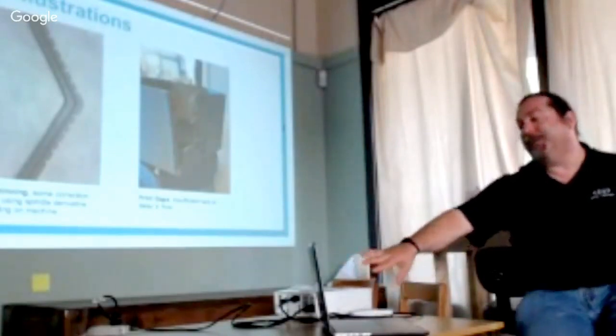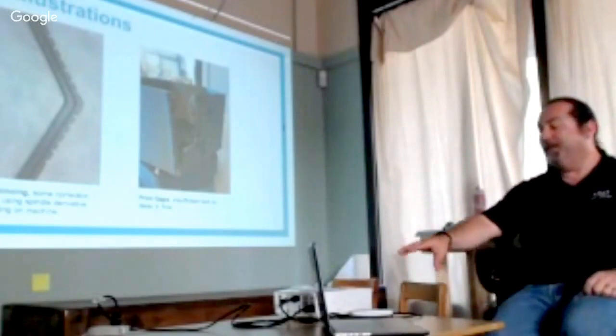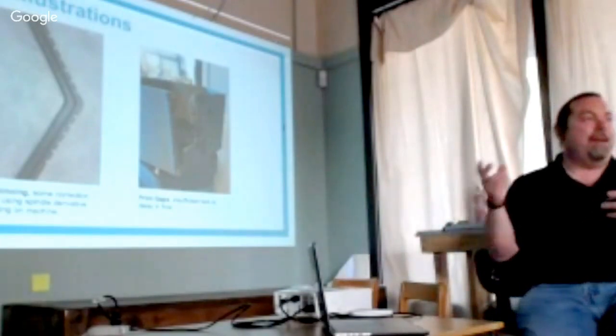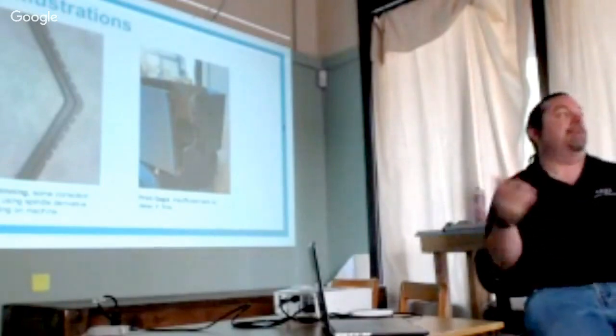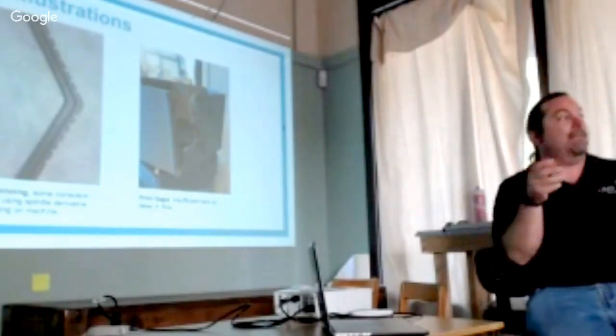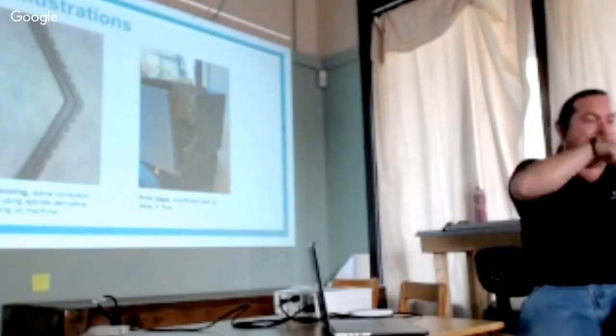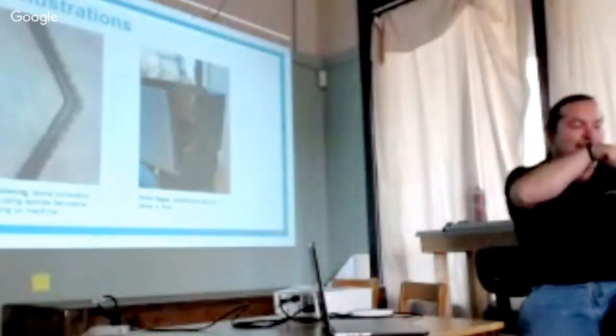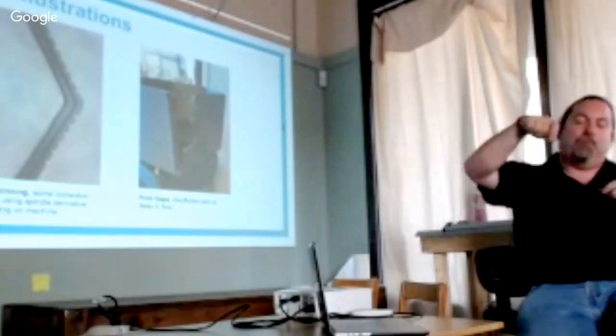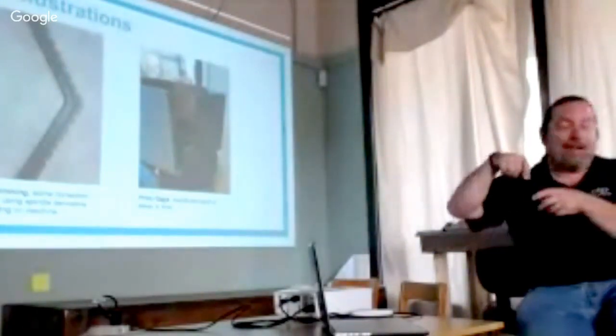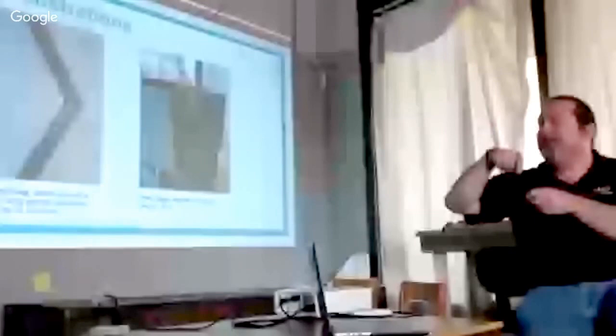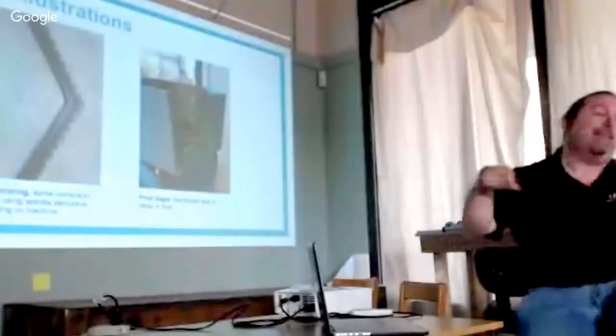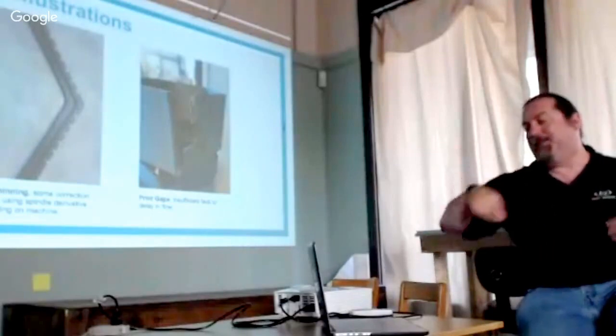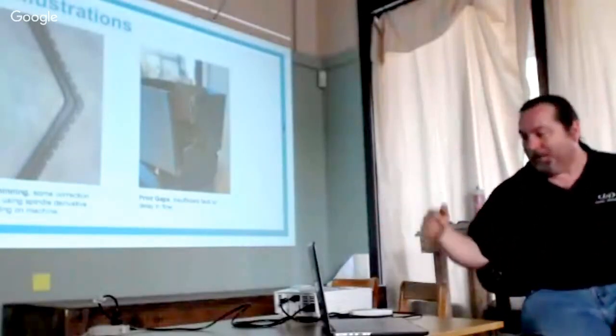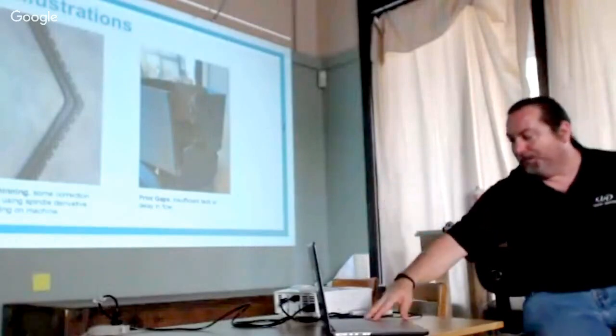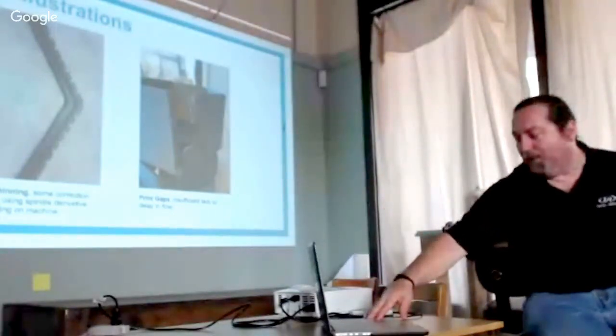And then this shows a print gap, and that's really catastrophic. In this one, it was due to the manufacturer adding some lubricant to the material to try to improve the rheology, the viscosity of it, but it didn't stick as well. So it just pulled off. If it goes around a corner and has insufficient tack, it doesn't stick and it can pull off. And once that happens at one layer, the next layer doesn't have anything to attach to, and it just continues around. We went ahead and finished this print because we can still do testing on the other walls, but that one wall was not good.